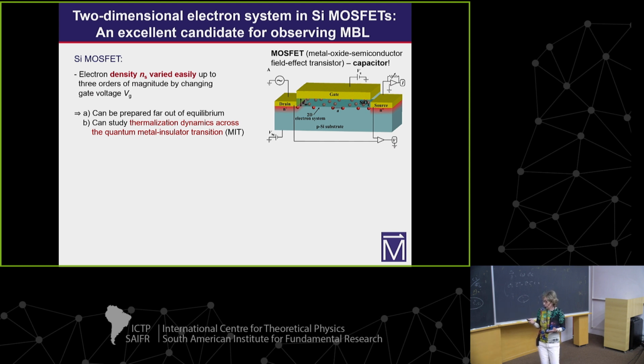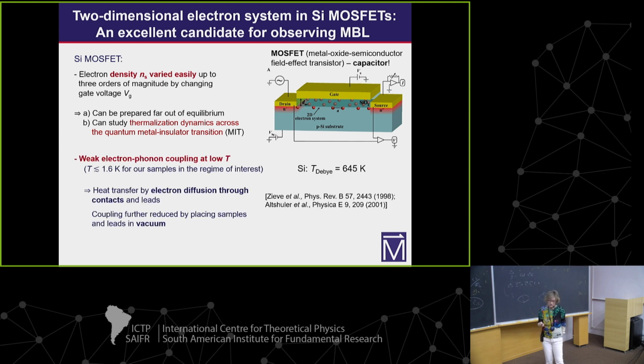The other requirement, we need this system to be well isolated thermally from the bath, and silicon is wonderful because the Debye temperature is huge. It has been known to everyone who ever worked with silicon that at temperatures below a couple of Kelvin, there are basically no phonons. This is why it's more difficult to cool the electrons at low temperature.